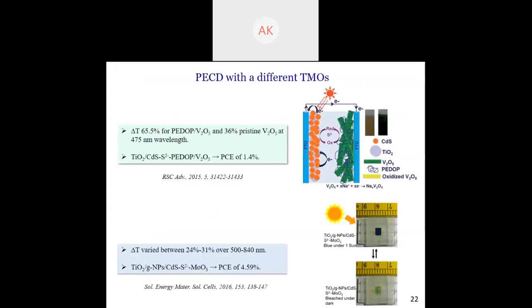They used molybdenum oxide. So for molybdenum oxide, the del T varied between 24% and 31% over 500 to 840 nanometer. And the power conversion efficiency achieved was 4.59. Now, in one of my previous slides, I have talked about the ways of improving solar energy. One point was carbon material addition. So here I've tried adding graphite nanoplatelets. This improved the conductivity of the cell and also enhanced the energy charge profile throughout the cell.